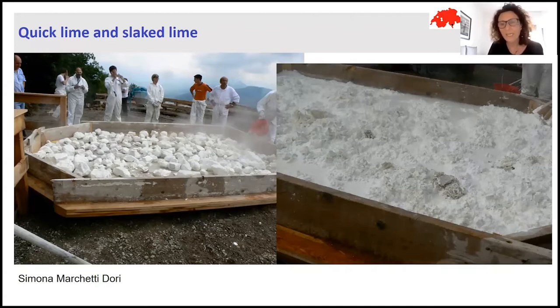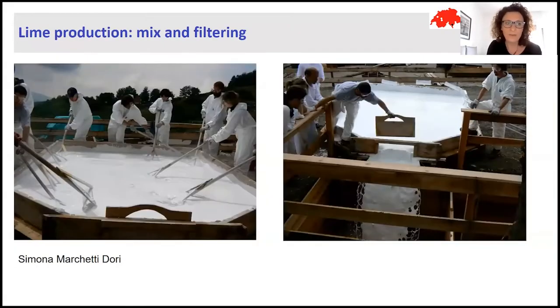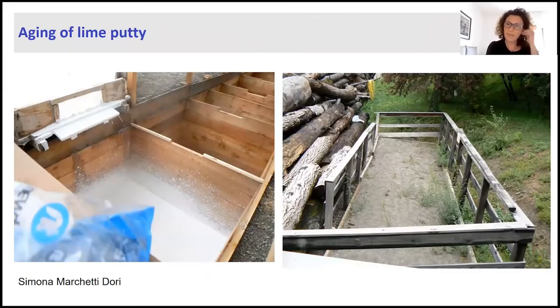Through an exothermic process with the production of heat, we can obtain the calcium hydroxide, and so, in excess of water, the lime putty, which is what I use for mixing and preparing the mortar. Then the lime was normally also better prepared by being mixed and also filtered in order to eliminate the unreactive part that can remain as residues in the lime putty. Another important process is the aging of the lime putty.